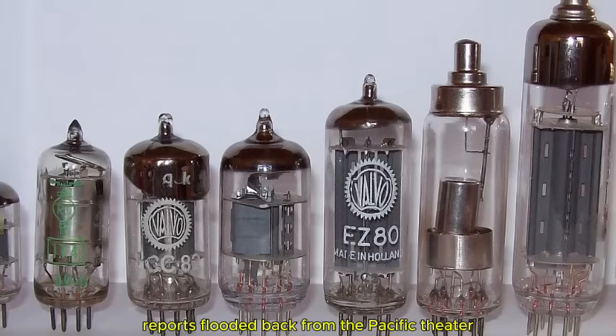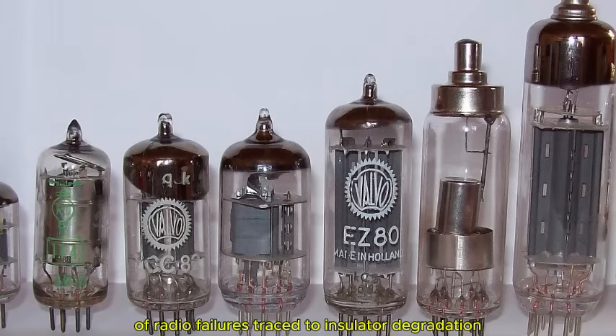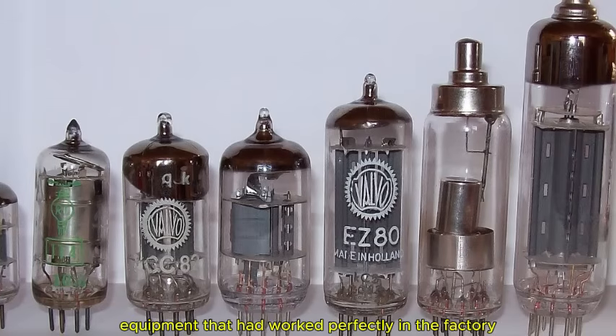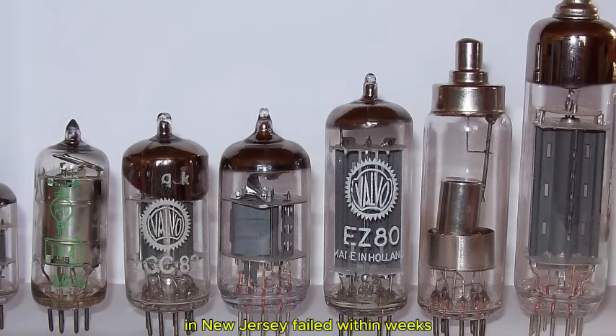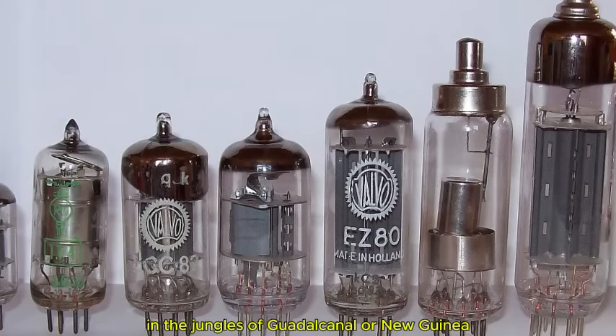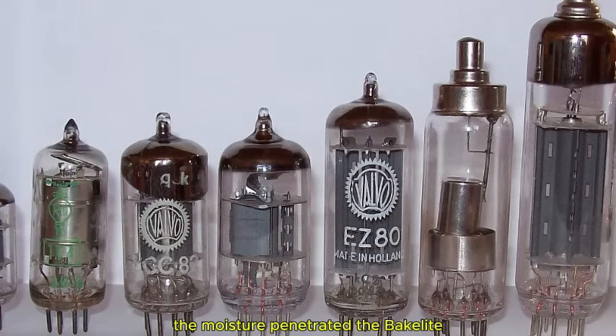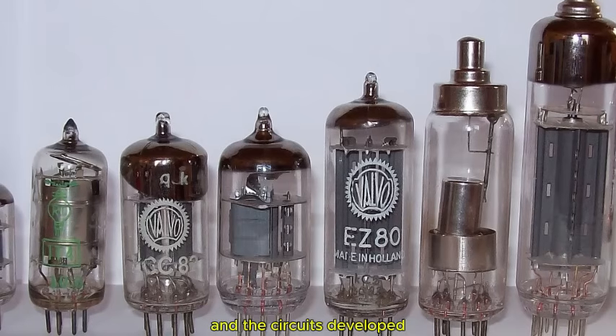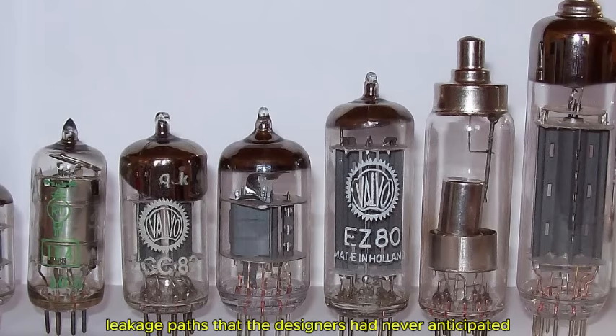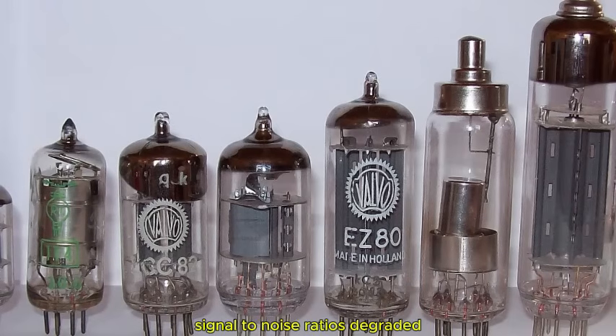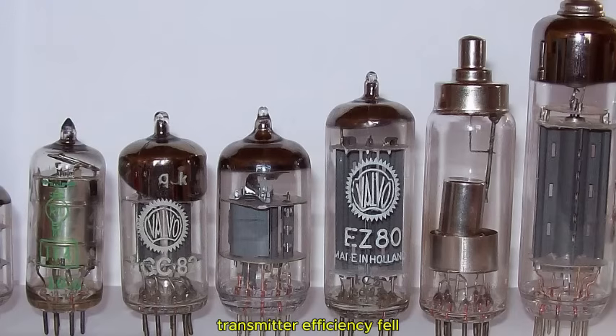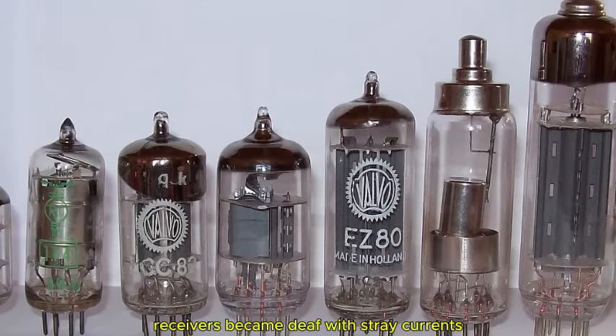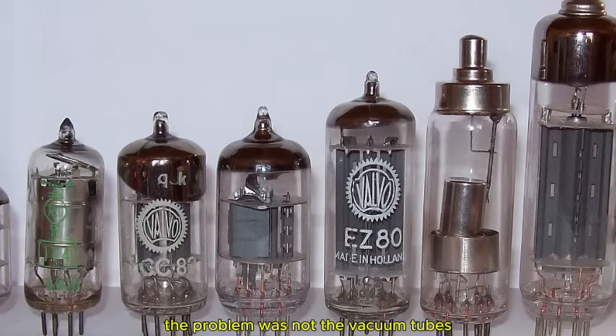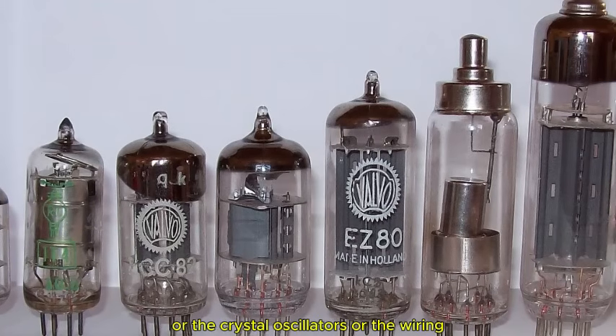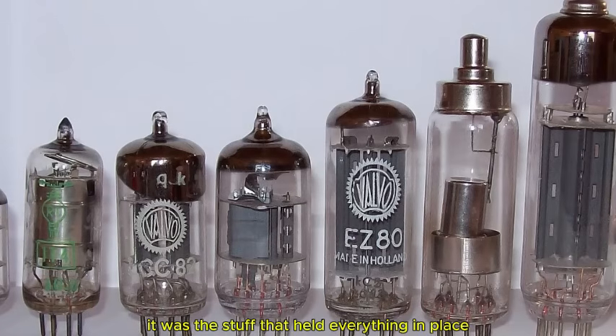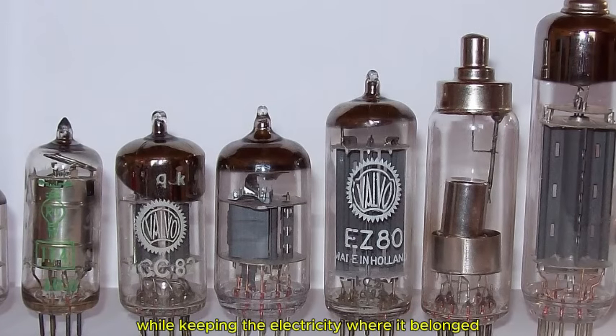Reports flooded back from the Pacific theater of radio failures traced to insulator degradation. Equipment that had worked perfectly in the factory in New Jersey failed within weeks in the jungles of Guadalcanal or New Guinea. The moisture penetrated the bakelite, the electrical resistance dropped, and the circuits developed leakage paths that the designers had never anticipated. Signal-to-noise ratios degraded, transmitter efficiency fell, receivers became deaf with stray currents. The problem was not the vacuum tubes or the crystal oscillators or the wiring. It was the stuff that held everything in place while keeping the electricity where it belonged.